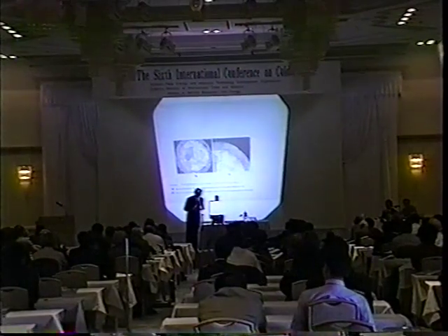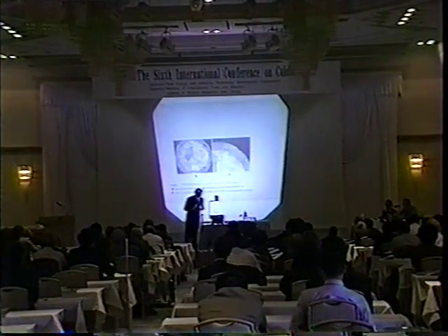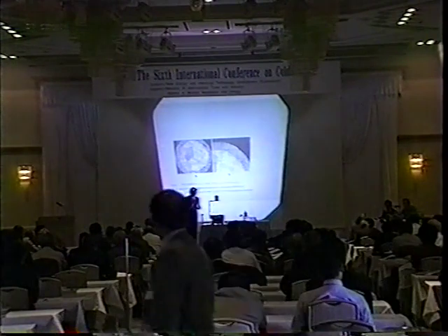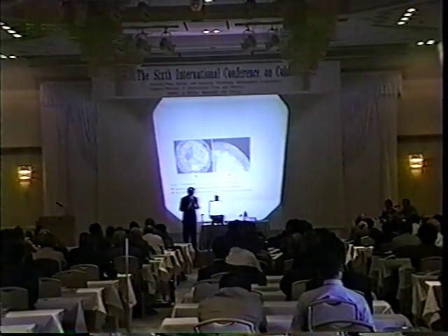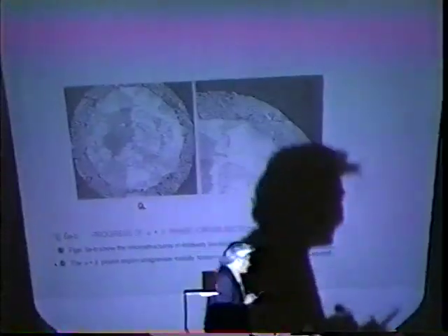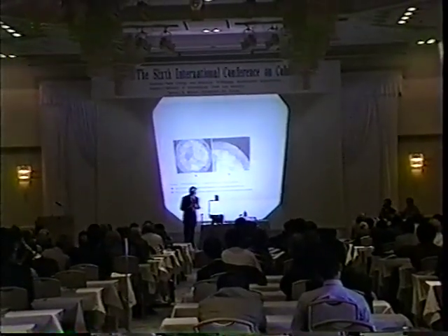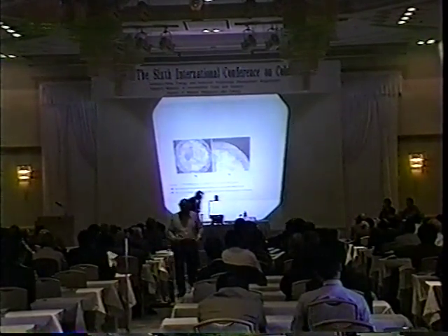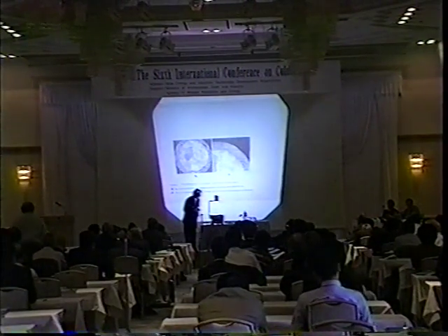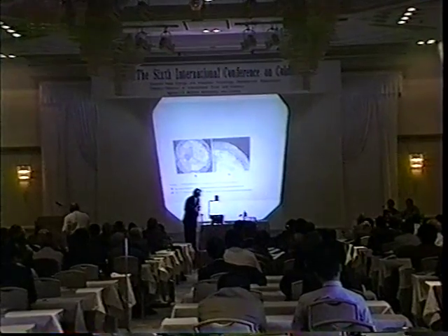You mentioned that the deuterium ions can go to the octahedral position up to unity loading. Is there any evidence that you can get tetrahedral loading? I mean, when they're in octahedral loading, the separation between deuterium ions is 2.74 angstroms. Is there any evidence you go to tetrahedral loading when the separation is reduced to 1.74 angstroms? In your talk, you mentioned that octahedral sites were occupied up to unity loading. My question is, is there any evidence that you can get tetrahedral sites being occupied? T site? Tetrahedral, yes.